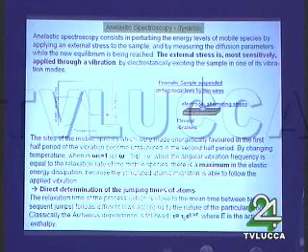If a stress is applied, for instance, horizontally in the present case of the figure, the green sites are made energetically favored with respect to the red sites. So we have a redistribution among the favored sites, and consequently an alignment of the distortions, and macroscopically we observe a time-delayed strain called anelastic strain, which is summed to the elastic instantaneous strain.